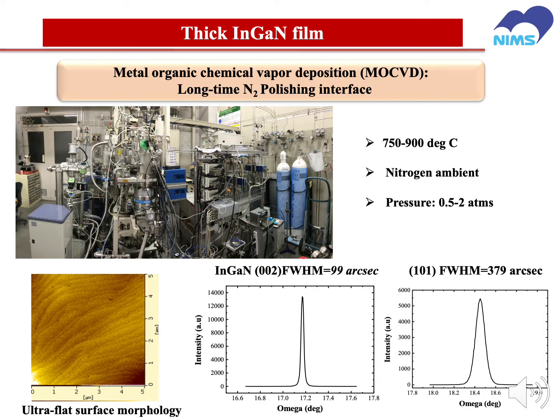For both the visible-blind photodetector and the solar cell, to improve the quantum efficiency it is necessary to obtain enough light absorption. This requires the indium gallium nitride film to be very thick, for example, around several hundred nanometers. Here we use metal organic chemical vapor deposition for the growth of the indium gallium nitride material. This is our material system, and the device structure is like this.